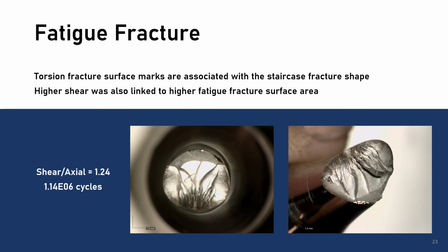Now, the torsion fracture surface marks are associated with this staircase fracture shape. And here, in the case of 1.24 shear and axial ratio, the effect of shear is quite predominant in the entirety of the fatigue fracture surface.